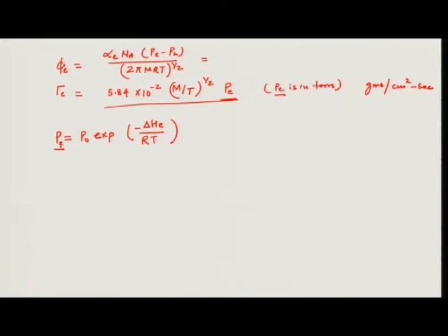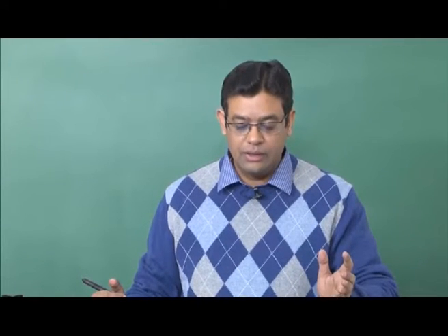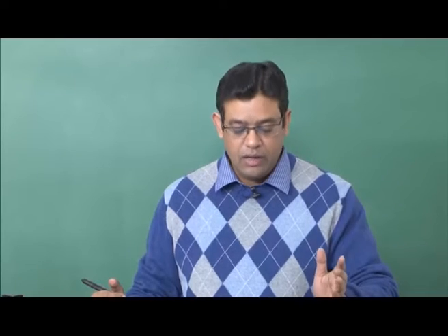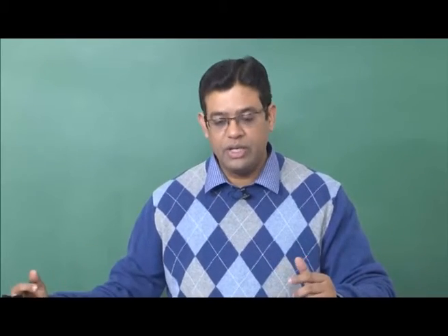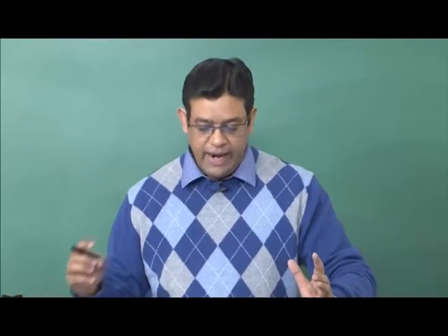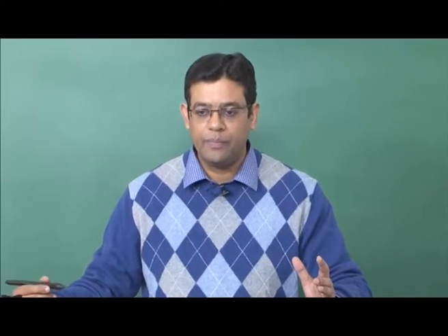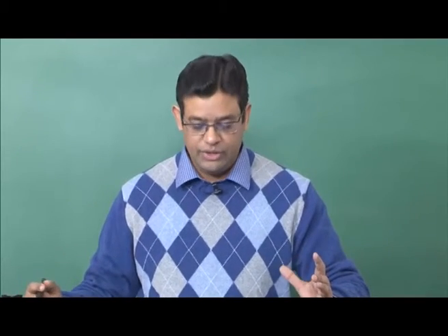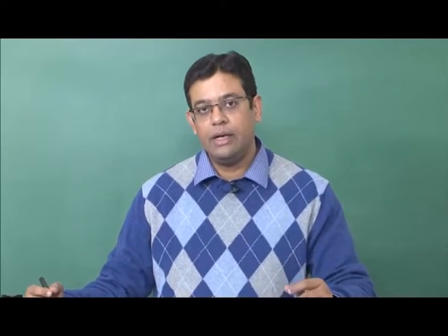Now, so far so good, and we had also discussed the vapor pressure curves with temperature for several elemental materials, and we had said that for thermal deposition the vapor pressure at that temperature should be around 10 to power minus 3 torr range. Okay. We had also seen the difficulty in evaporating